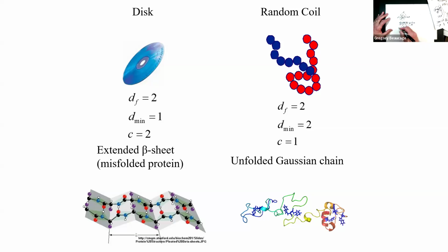So this is where the coil sets up a new size scale in order to accommodate the pulling on it. You have the size scale R, and then you still have a size scale R that's larger because you pulled on it and it got longer, but there's a new size scale that shows up, this kind of correlation size. That's determined by a balance between kT and the force that you put in. Force times distance is energy, kT is energy. So this gives you this screening size.